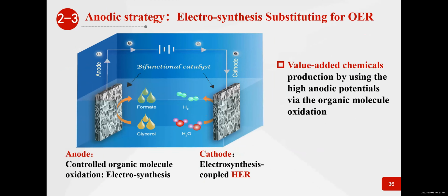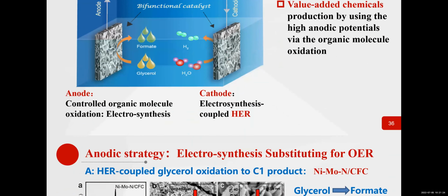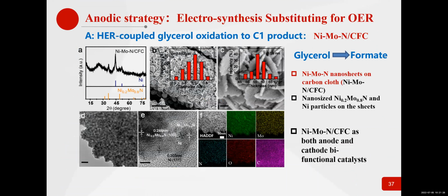Okay, here is our schematic. At the cathode, it is a common HER process by water splitting. And at the anode, we try to achieve controlled organic molecule oxidation for the electrosynthesis of some kinds of chemicals. Here, for example, we try to use glycerol. Glycerol is used as a substrate to substitute for the OER, and by the oxidation of glycerol we can obtain formate as the product, and in this process we use a catalyst. It is nickel-doped molybdenum nitride nanosheets.